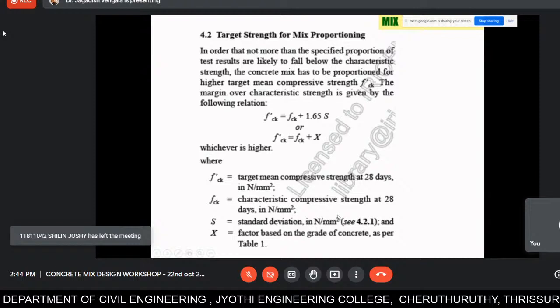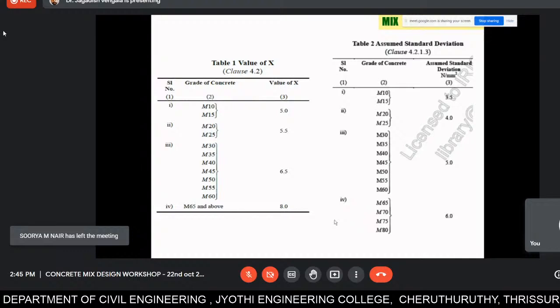So the first thing is we have to find out the target strength. The target strength formula: f_ck' equals characteristic strength plus 1.65 times the standard deviation. Otherwise, you can take the X factor based on the grade of concrete, as given in IS 10262 2019. Standard deviation, you can consider 3.5 for M10 and M15. But for RCC, the minimum grade of concrete is M20, so for M20 and M25, take 4 as the standard deviation. For M30 to M60, take 5, and for M65 and above, up to M80, 6 is the standard deviation. Otherwise, you can add the X value, either 5.5, 6.5 or 8, as the additional strength.